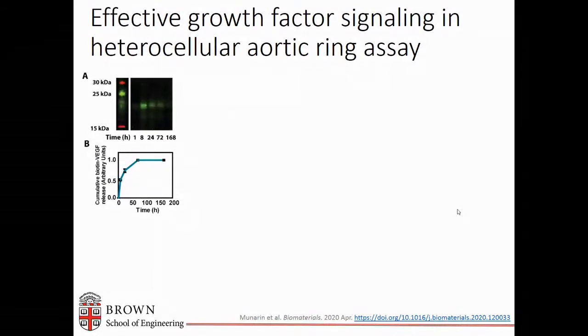So in order to look at release of our growth factors from these alginate microspheres, again, this is unmodified alginate, we used a labeled biotinylated VEGF loaded in the microspheres, and we looked at this time course of release. And you can see from the Western blot and then here quantified that over 3 days, we get all of our protein released.